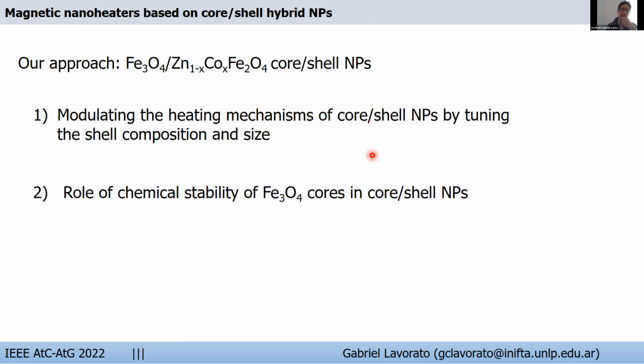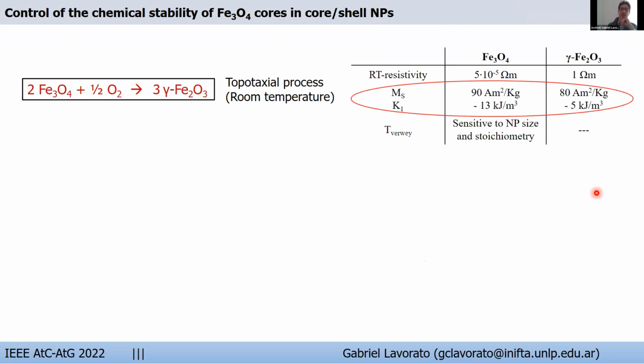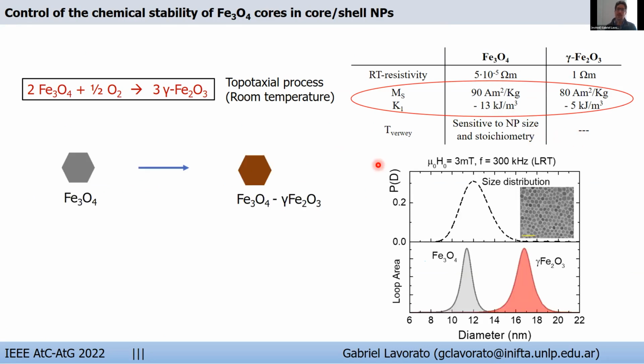So before ending my talk, I will briefly comment on another result regarding the chemical stability of magnetite in these core shell structures. So it is known that magnetite nanoparticles gradually transform into maghemite at room temperature, leading to a decrease in the magnetization and in the anisotropy, while the Verwey transition, which is characteristic of magnetite, is no longer observed after its oxidation to maghemite. So if we oxidize our 12 nanometer magnetite cores for some time, then we will have maghemite in the system, and this will drastically change the optimum size for achieving large heating powers, as shown in the simulations here on the right.